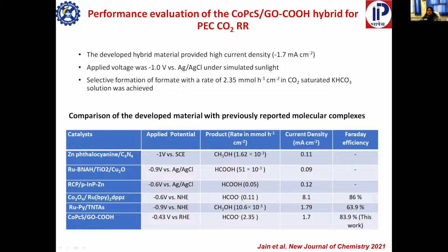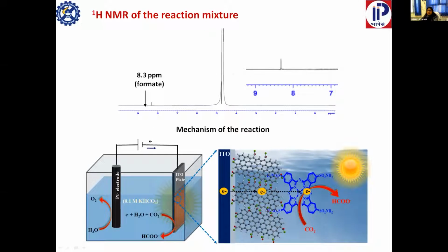it should give the formate at a rate of 2.35 millimole per hour in the CO2 saturated potassium bicarbonate solution. If we compare our system with the literature known systems, we can see clearly that the system we have developed is found to be more efficient than the prior art methods. Similarly, this is the reaction product, how we analyze the product by 1H NMR using an internal standard. And this is the reaction mechanism.